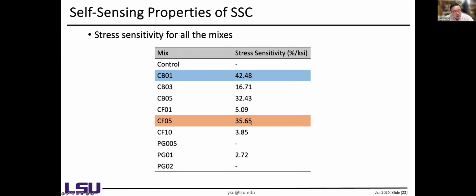So we further move to evaluate the stress sensitivity, because if that is sensitive enough, then it will be great for structure health monitoring. And we found the CB01, CB05 give us a really great signal, as well as CF05. However, as I mentioned before, for the sample incorporating the carbon black, the rheological property as well as the mechanical property is not as good as the sample incorporating the mule carbon fiber. So we determined to use the mule carbon fiber mixture for our 3D printing purpose.